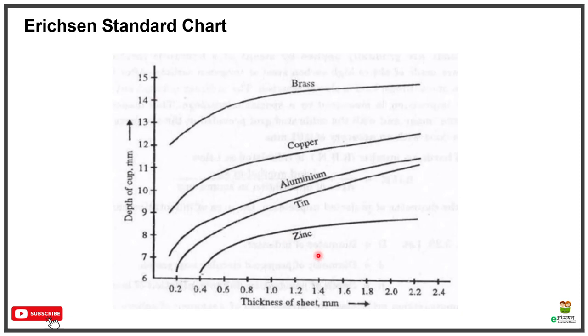If you go from bottom to top, the depth of the cup increases. That means the ductility of the material increases. Even with higher thickness, we get very good ductility. So these top materials are very good for deep drawing or drawing process, or for forming and manufacturing processes. Brass, copper and aluminum are the excellent ones to be used for the forming process. However, brass and copper are costlier than aluminum.